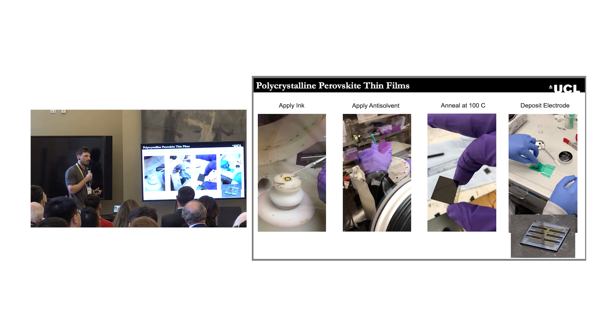You can do a number of processing things. You can either co-evaporate your charge transport layers, or you can even do things such as what I like to call scotch tape-assisted doctor blading, which is you can literally take a piece of scotch tape, put some holes in it as your mask, and then apply a paste of carbon which you can buy from Alibaba for about one pound over the top of your substrate. You end up with these fingers of carbon electrodes. The process is literally you just take a microscope slide and wipe it across your mask, and that's it. You have your solar cell. These are about 20% efficient, and that's all done relatively easily. You don't have any high-temperature processing.